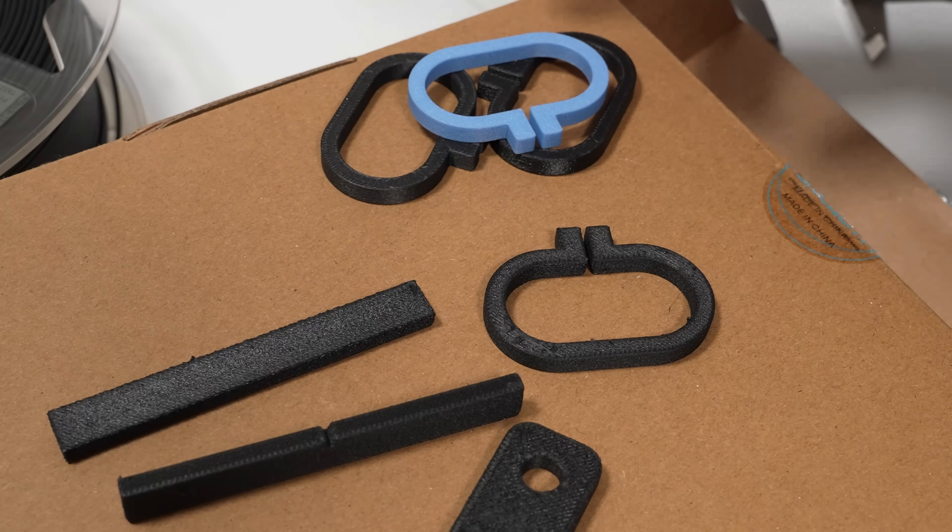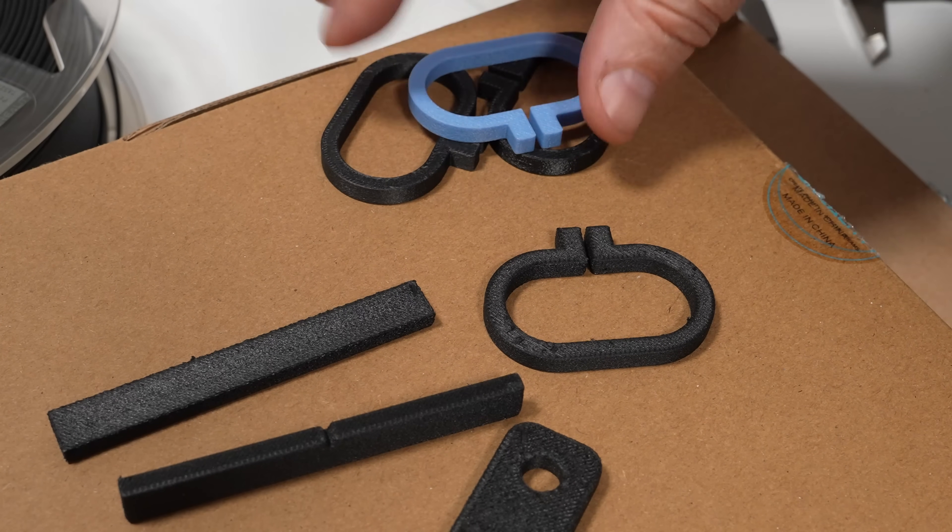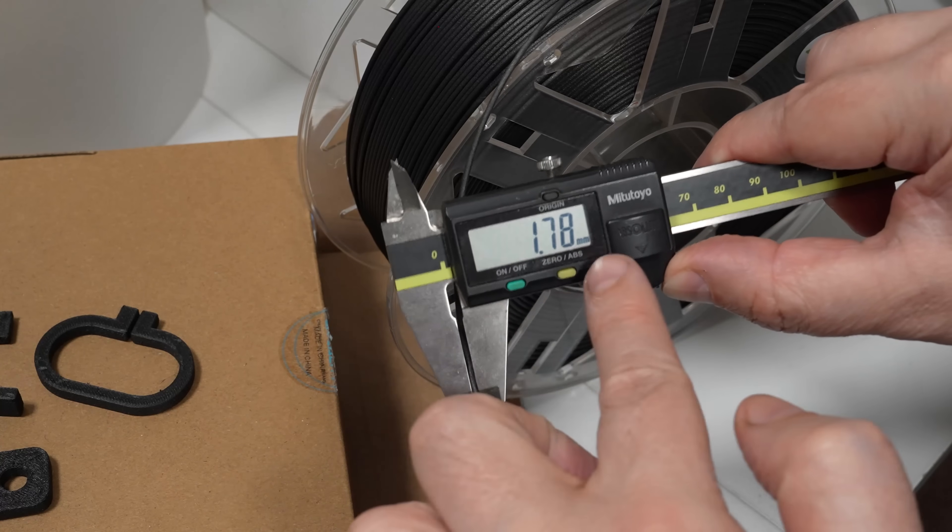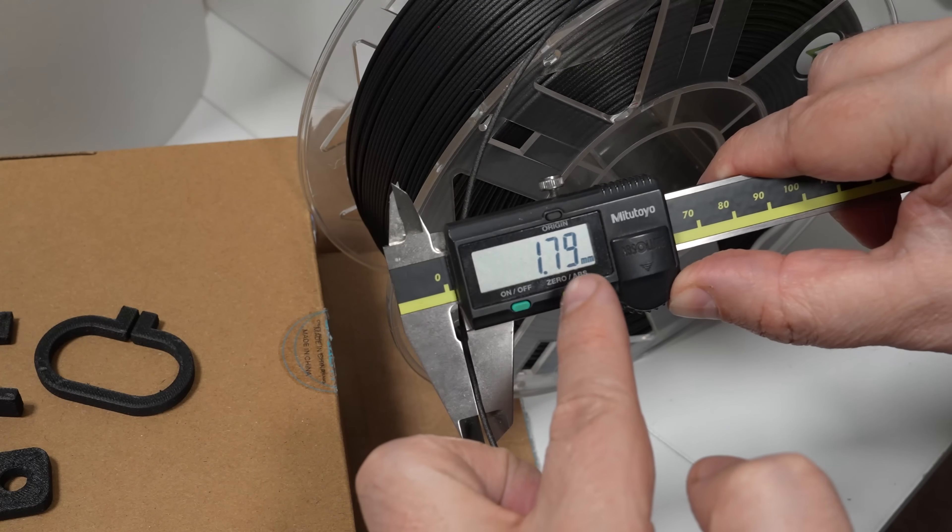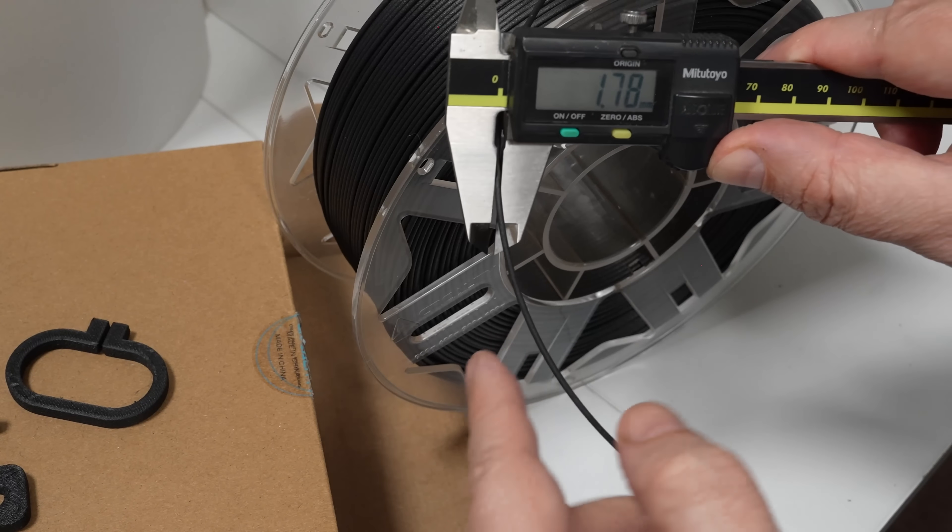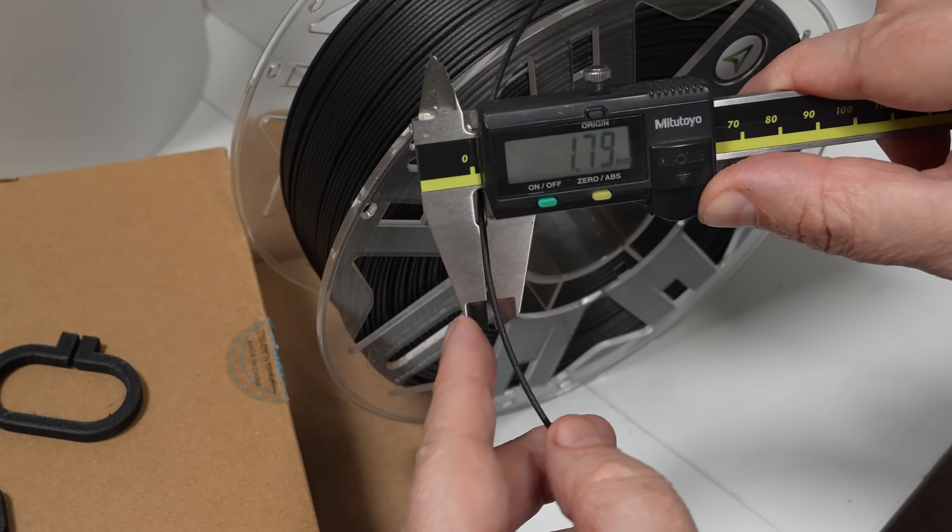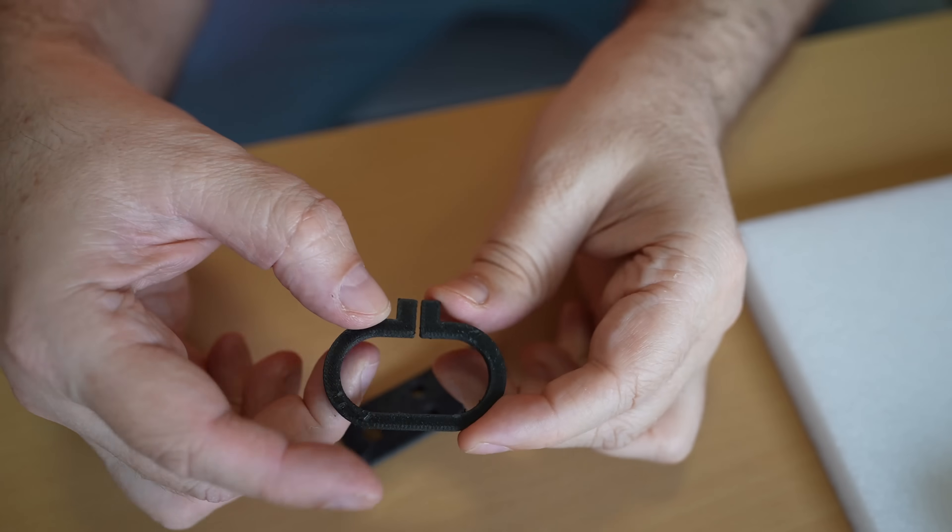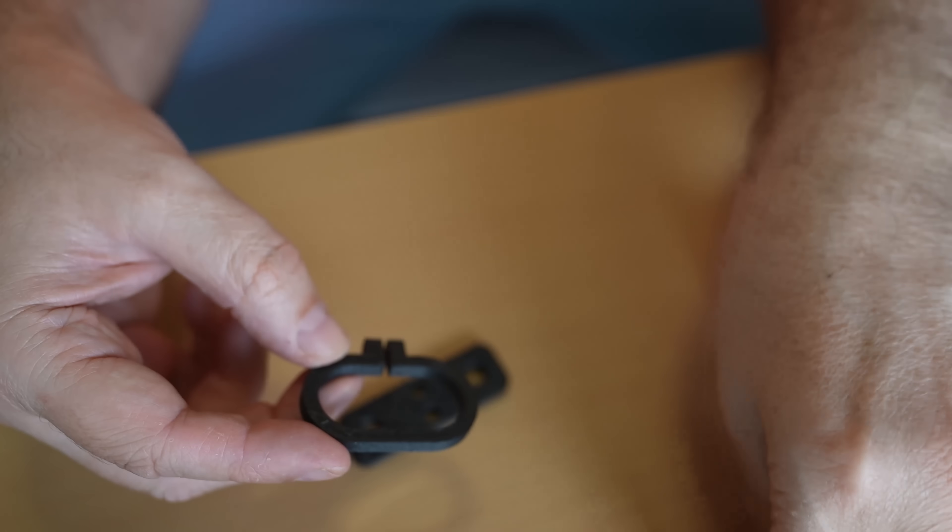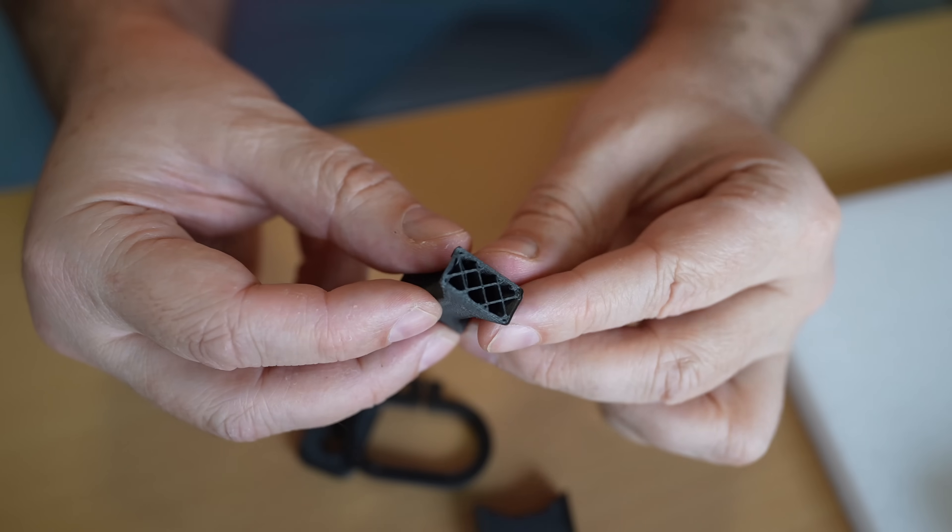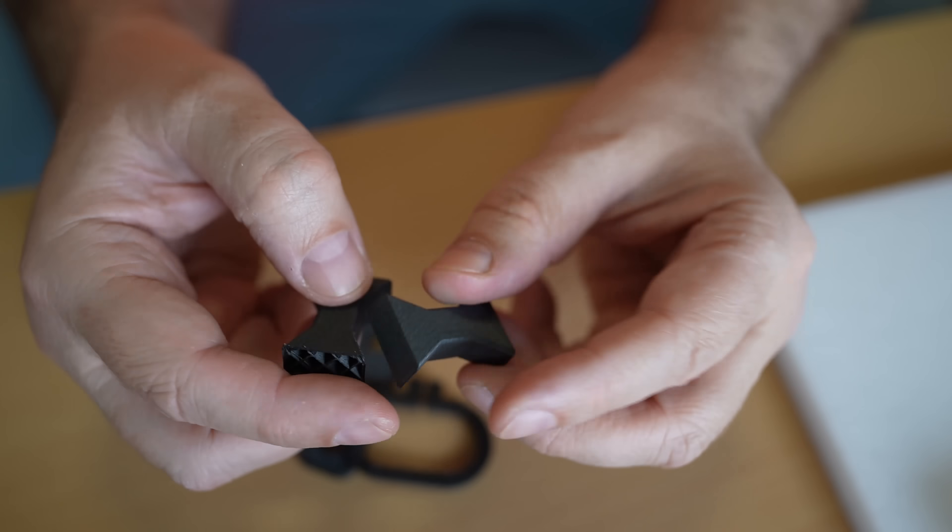I can compare it now because I have several PPA materials testing in progress. I checked the filament diameter and at some points it's slightly bigger - 0.04mm bigger in diameter, but only on some points. I'm not sure if this is really normal and causing this problem. The result is not always so bad - my test objects are solid inside, but if we use infill less than 100% the material has space to go.